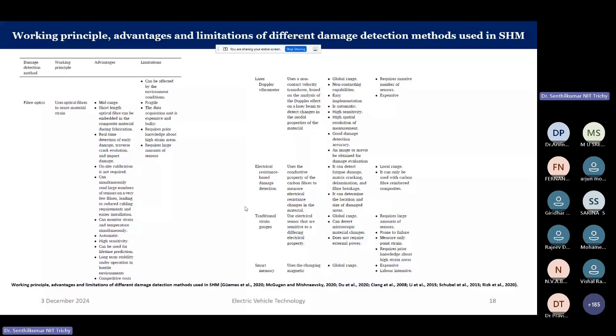Then on-site calibration is not required, can simultaneously read a large number of sensors on very few fibers, leading to reduced cabling requirements and easier installation, can monitor strain and temperature simultaneously. Then it has sensitivity that can be used for lifetime prediction, long-term stability under hostile operation environments, competitive cost. Then the limitations are that it can be affected by the environmental conditions, fragile, the data acquisition unit expensive and bulky, requires a prior knowledge about the high strain areas, requires a large amount of sensors.